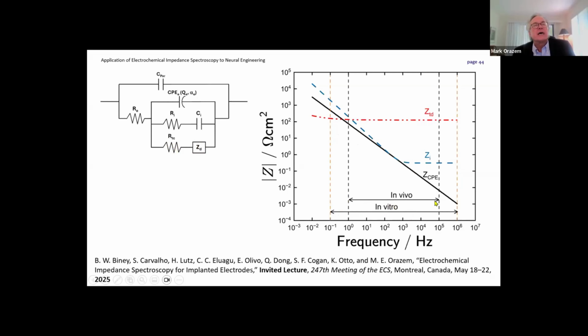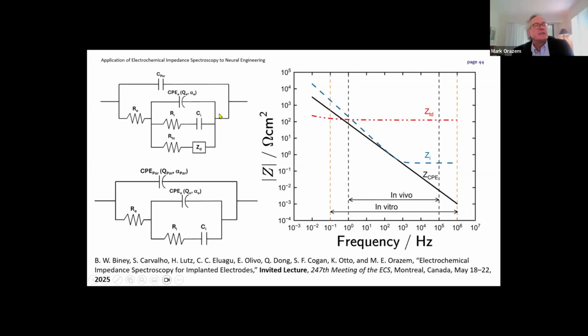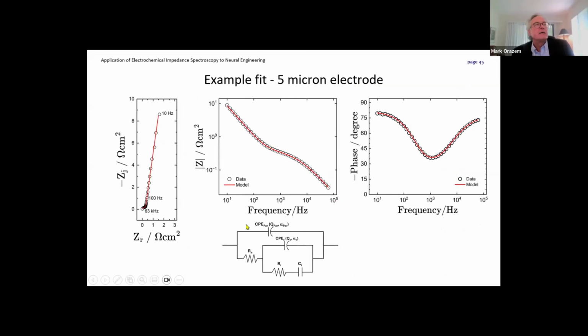But in vivo, we cannot have such a large frequency range. And so in this particular case, if we say that 1 hertz is a lower frequency, we really cannot capture this behavior. So we end up having the same model, but without the reduction of oxygen as part of the model. It doesn't mean it's not there. It's just that the frequency range we used was not sufficient to allow us to see it.